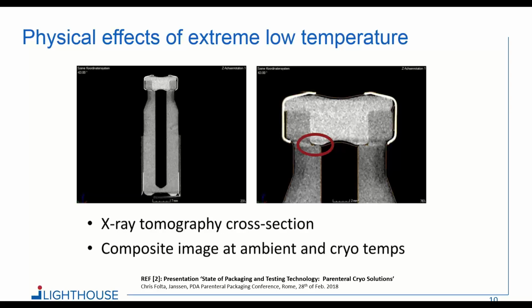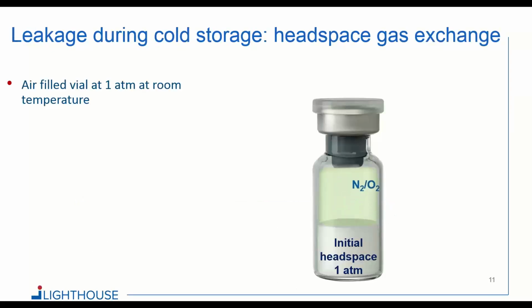And of course, this can cause a potential risk to the actual closure of the vial. So what happens if you actually lose closure during deep cold storage? So we've put together some animations here, which hopefully make this a little bit more clear. So imagine you have an air-filled vial at 1 atmosphere at room temperature. So it's been filled, it's under an air headspace, it was capped and crimped, and it actually has good closure. So it's well sealed.